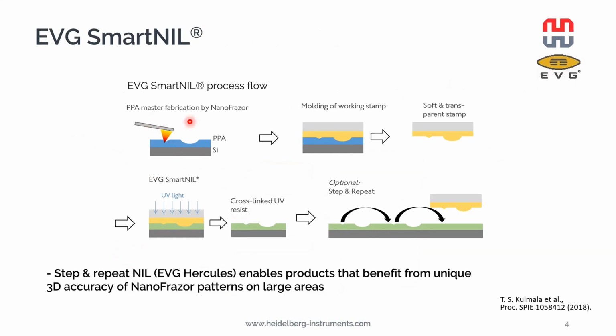So what we did, we first patterned a PPA master. In this case, the master was just our thermal resist PPA. And we sent them to Austria for the processing, where they produced the working stamp by molding the working stamp material and attaching a transparent backplate on it. It was just peeled off mechanically to create a negative image of the original patterns. In the next step, the stamp was pressed against the NIL resist, and UV light is exposed through the transparent backplate in order to cross-link the resist and to make an impression into it.